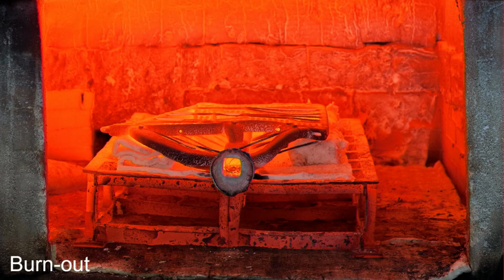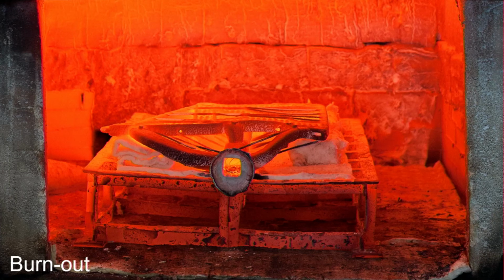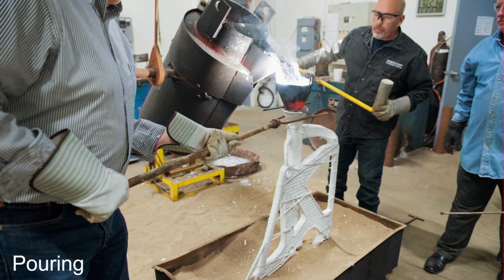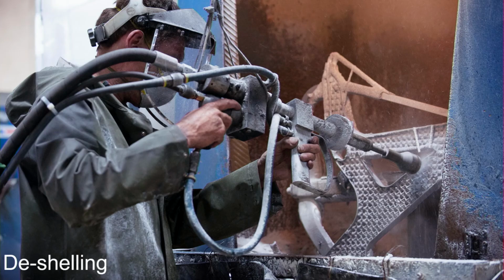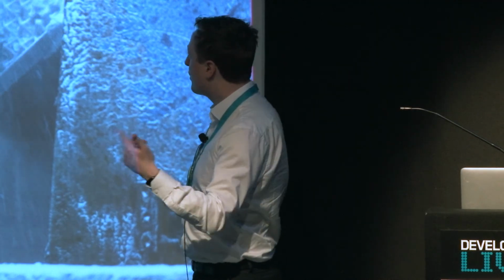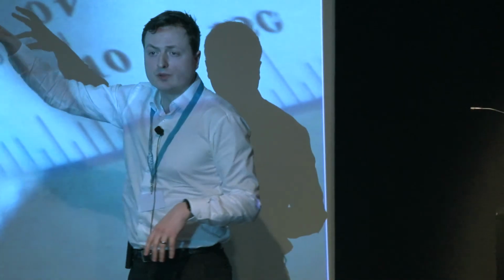This is where your choice of design and material that you use for your pattern is very critical. If you have a plastic that expands too much, it will crack that mold. So you need something that's not going to cause that mold to fail. And then we're pouring in the material. In this case, we're pouring in magnesium. So that component you'll see on our stand is made from magnesium. And then we've got a de-shell. So this is where you've got to be careful with lattices. You can cast maybe 1 or 2 cells thick in lattices. Start going more than that, then de-shelling becomes difficult. So you end up with the shell stuck in the middle, potentially.